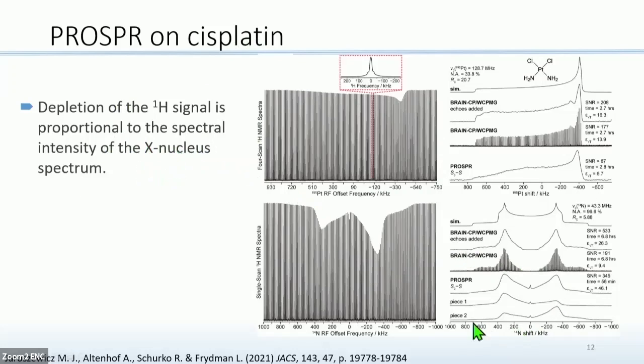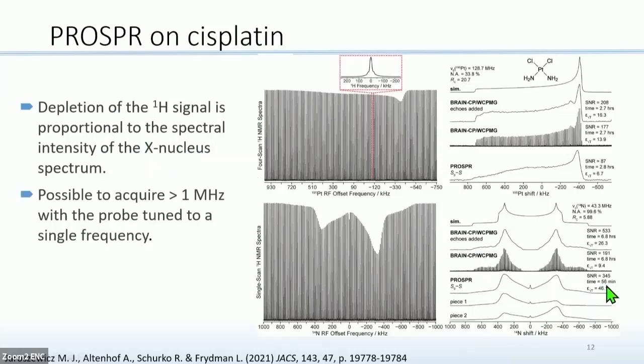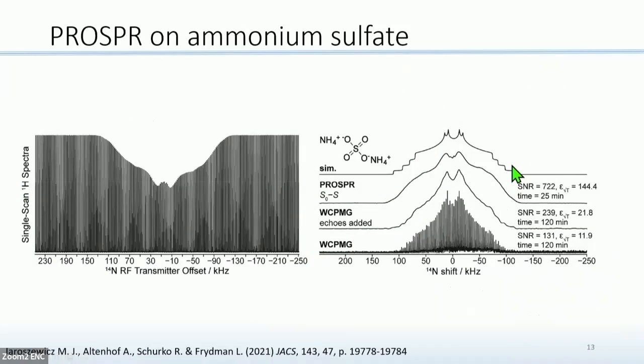We see here that especially for nitrogen, for N14, we do get enhancement from this method. Also, a very nice feature that we encountered is that we were able to acquire over 1 megahertz in frequency with a probe tuned to a single frequency on the X channel. Usually for BRAIN-CP, we had to acquire it at 7 or 8 different offsets. Another compound that we checked was ammonium sulfate, and here we got even more significant SNR enhancements.